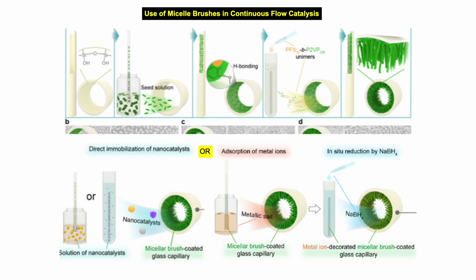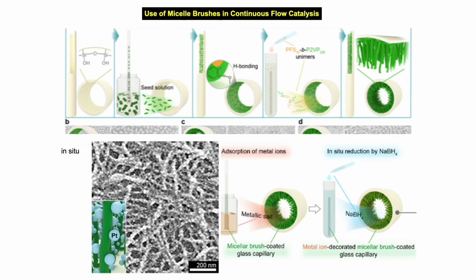You can do this by two methods. You can make the nanoparticles first and then just add them and they will stick. Or you can do a two-step in situ reaction where you start with a metallic salt and then reduce this down to the metal which forms the nanoparticles, and then they stick to the brush layer. Here's an image of these brush layers with particles attached.